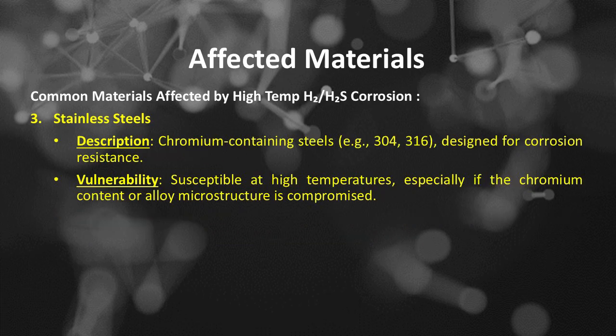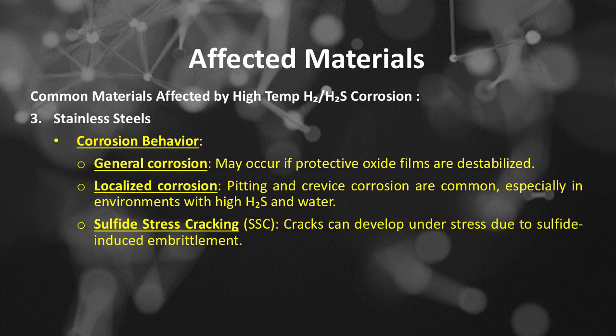The affected materials, number 3, is stainless steels. Chromium-containing steels, such as 304, 316, designed for corrosion resistance. The vulnerability of the stainless steels: susceptible at high temperatures, especially if the chromium content or alloy microstructure is compromised. The corrosion behavior of high-temperature hydrogen (H2) and hydrogen sulfide (H₂S) corrosion on these stainless steels includes general corrosion, which may occur if protective oxide films are destabilized; localized corrosion, where pitting and crevice corrosion are common, especially in environments with high hydrogen sulfide (H₂S) and water; and sulfide stress cracking or SSC. Cracks can develop under stress due to sulfide-induced embrittlement.